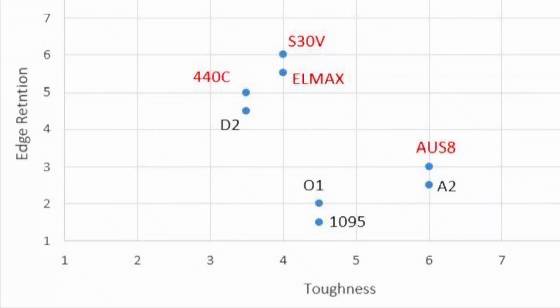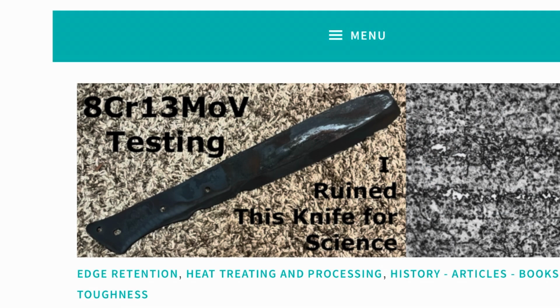All right, so here's some data I got from the Knife Steel Nerds website of Larrin Thomas, where he compared AUS8 to different steels. The stainless steels are marked here in red, and the non-stainless in black. So you can see that for stainless steel, AUS8 has some very good toughness, much higher toughness than 440C, S30V, or ELMAX. And if you compare it to a carbon steel, still has a very high toughness, much more than O1 or 1095. It's very comparable to A2 tool steel. So the edge retention is still pretty decent, still better than 1095 or O1, and very similar to A2. So in essence, we could say that AUS8 is a stainless steel version of A2, which is an excellent steel for mid-sized blades.